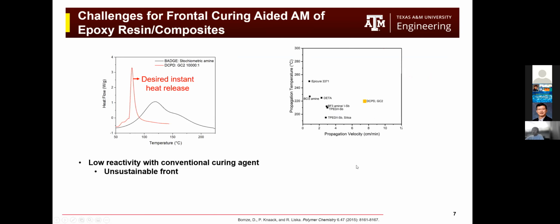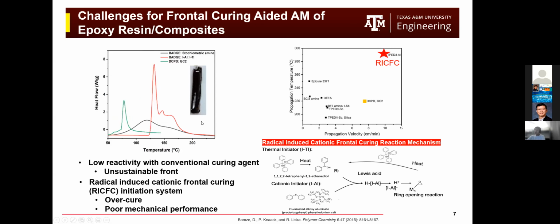However, one of the challenges remaining for using this material is that the traditional curing agent, which can be shown here, can cure the part, but the heat releasing profile is not desirable for the continuous self-propagating reaction. So for the desired heat releasing profile, we want a burst of heat release, so that the reaction can be sustainable. One of the solutions people have found is using radical induced cationic frontal curing to fabricate these epoxy composites. And we can see here the heat releasing profile is very desirable, which is a burst of heat release.